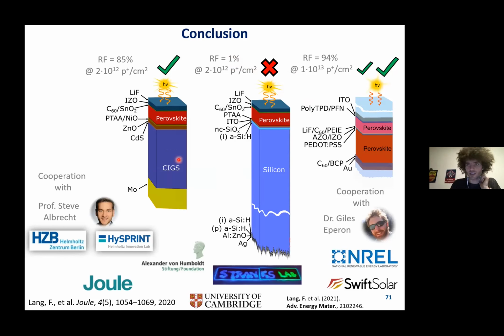Perovskite CIGS are a better choice, though there is some damage in the CIGS subcell and also some damage at the recombination layer. And then I looked at perovskite tandems, which so far showed the best results with a remaining factor of 94%. Both perovskites were extremely radiation hard, and most damage arose from the recombination layer in here. So this is something where we will need to work on just to increase the radiation hardness even more.